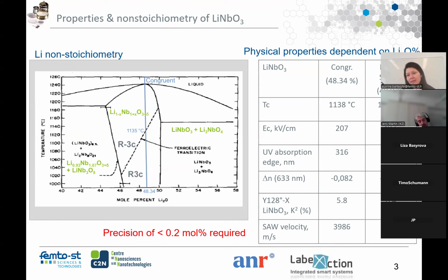And let's look at why it was difficult to grow the films and what we had to work on. So the first thing when we start to work with lithium niobate is to know that lithium niobate is a material which has a broad non-stoichiometry range. So very frequently we will write LiNbO3 in all the papers, but it's not true. The formula is Li(1-x) and so on. And normally the concentration of lithium is 48.3 mole % in the congruent crystals, in the crystals and the films which you are buying.